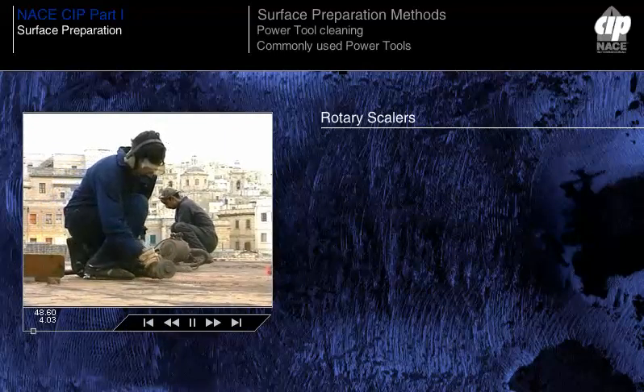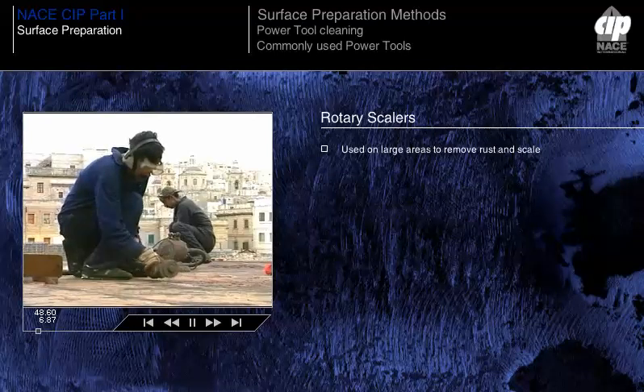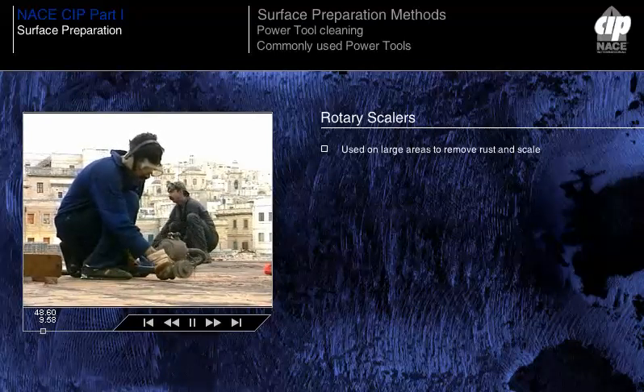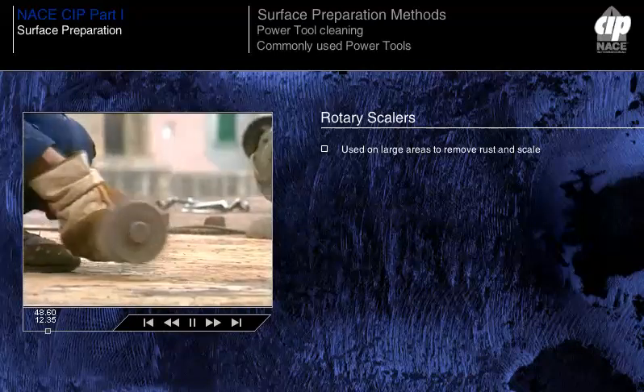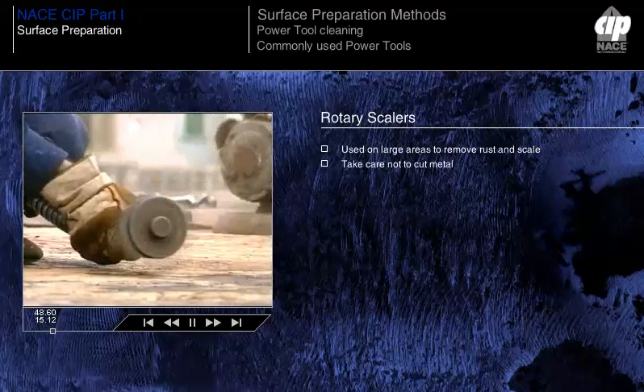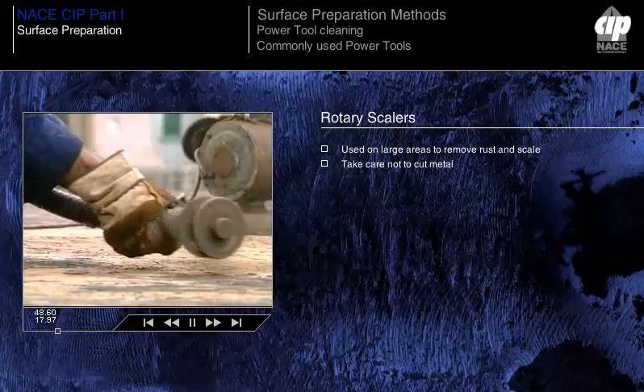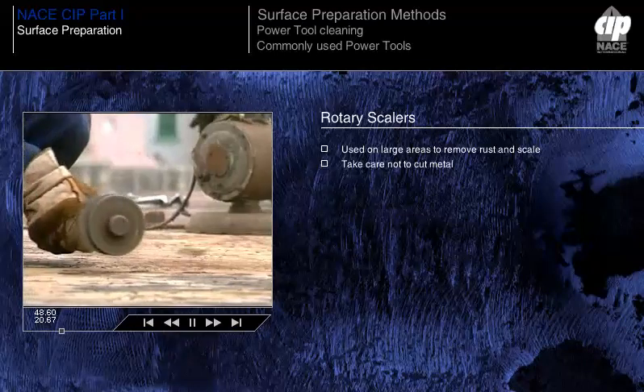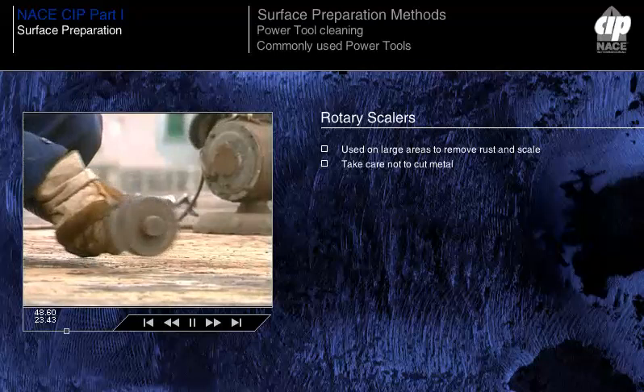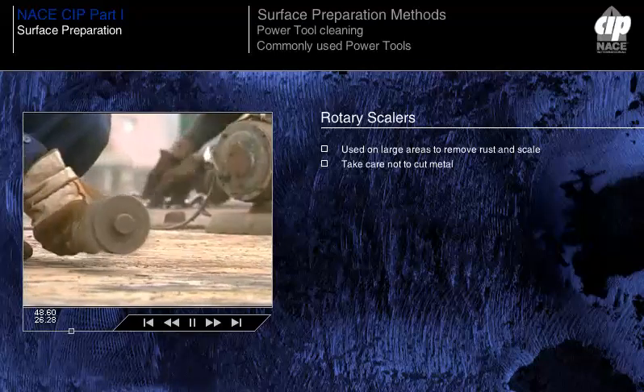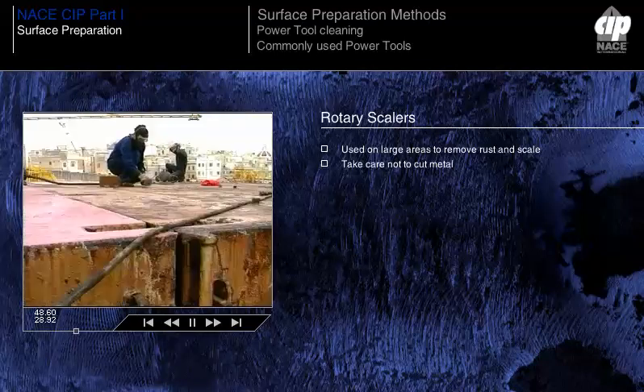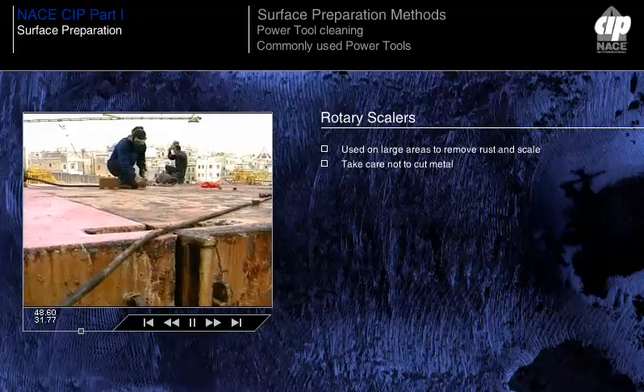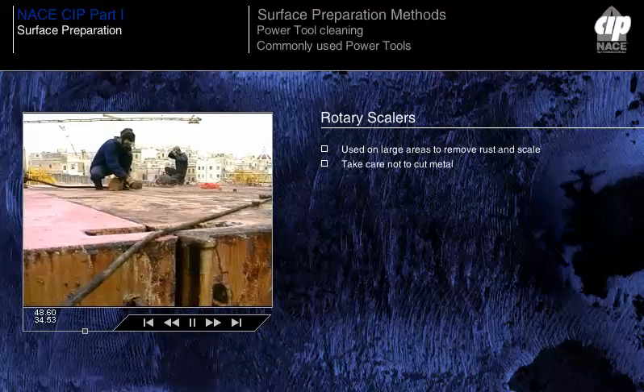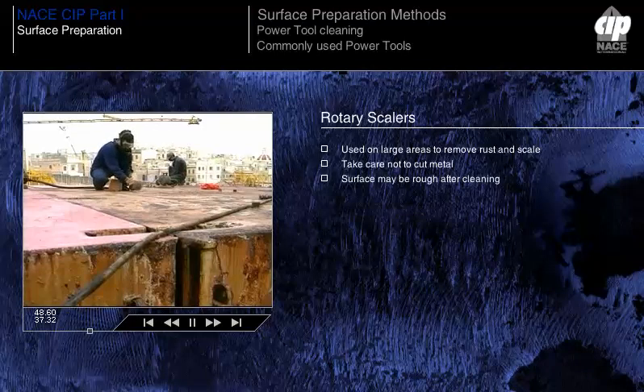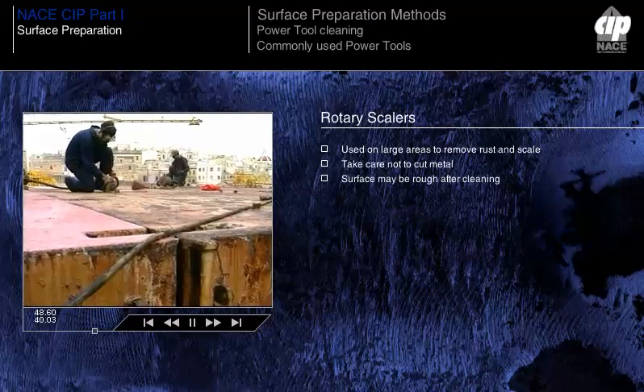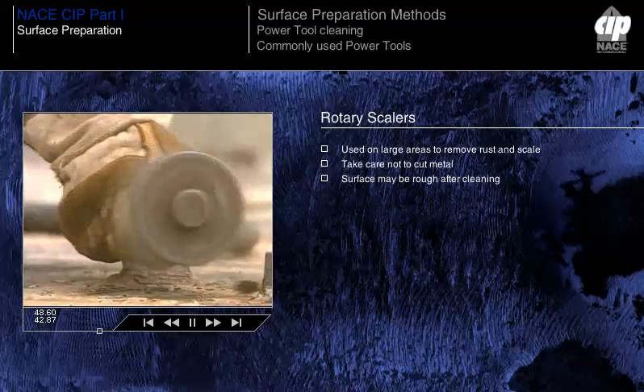These tools can be used advantageously on large areas to remove rust and scale. Care must be exercised to prevent the cutters of these large rotary scalers from cutting the metal to such an extent that metallic points extend far above the surface, causing early paint failure due to insufficient paint coverage. If these tools are used to remove mill scale and rust from the surface, it's very likely that the surface will be very rough, and care must be taken to ensure that all peaks of the anchor pattern are covered by the coating applied.